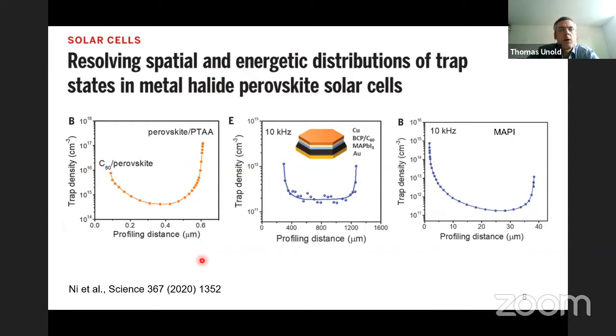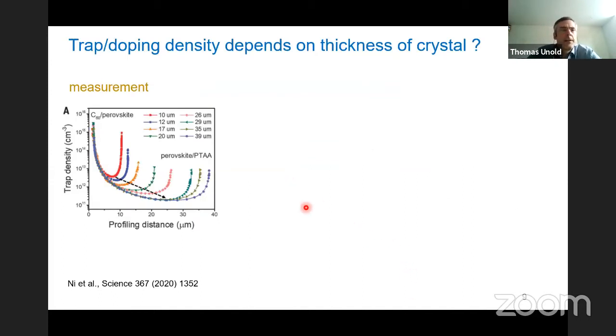using the same method. And now at this point, we were wondering, okay, we had done some simulations of these charge densities versus profiling distance for perovskites and found similar shapes actually, even without putting any doping into the simulation. So we were kind of worried about this, but then if you go further along reading the paper, they did an enormous amount of measurements and also synthesis of materials and devices, very nice work. And they made all these different crystals with different thicknesses from 10 to about 40 micrometers. And then they measured the trap density, and you can see now that the thicker the crystal gets, the lower the trap density gets.